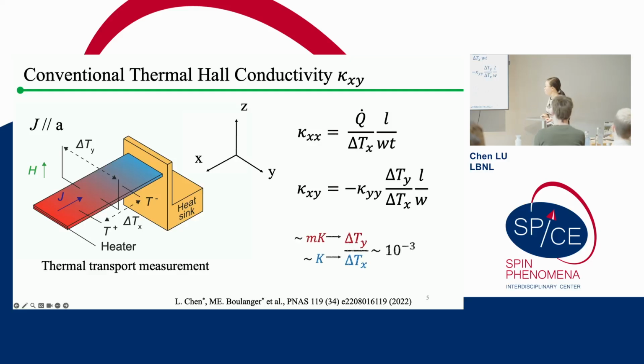One thing I need to emphasize is that for these types of thermal Hall effect measurements, the net signal you get along the transverse direction, delta Ty, is about 1,000 times smaller than the signal along the longitudinal direction. Generally, if you have a delta Tx of about several Kelvin, your delta Ty is about several millikelvin to tens of millikelvin. So this is a pretty hard experiment to perform, and you need extremely high temperature stability for your system.